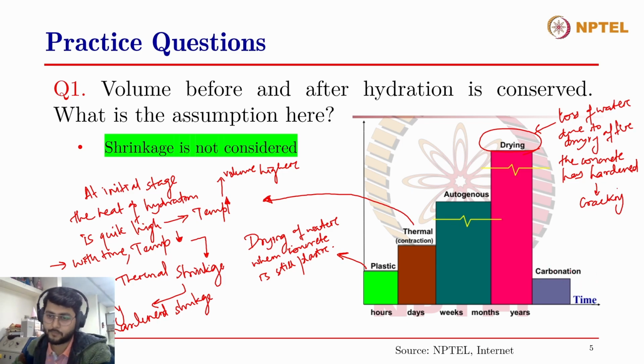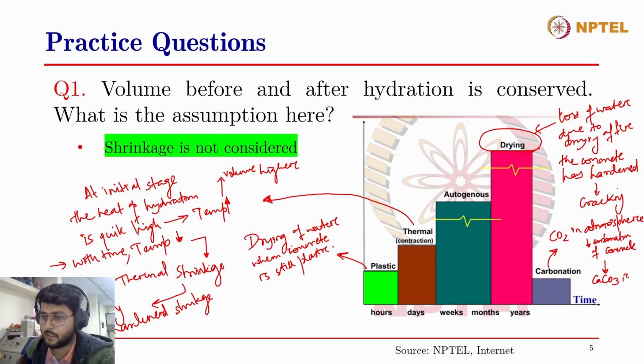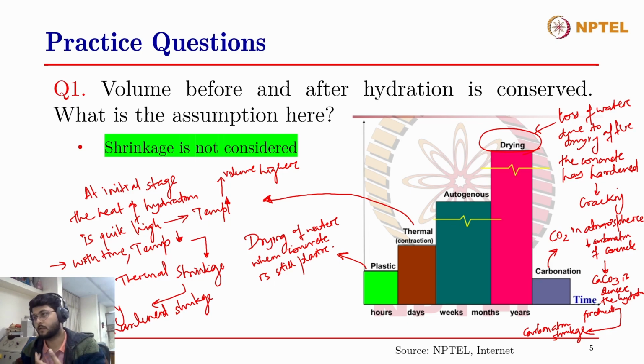And then the final one is carbonation shrinkage, and this occurs generally after several years, and this is due to carbon dioxide present in the atmosphere. When this carbon dioxide reacts with the concrete, it produces calcium carbonate, which is denser than the hydration products, and therefore carbonation induces a shrinkage. Because it is denser, it will occupy a lower volume, and therefore the concrete undergoes a certain amount of shrinkage.